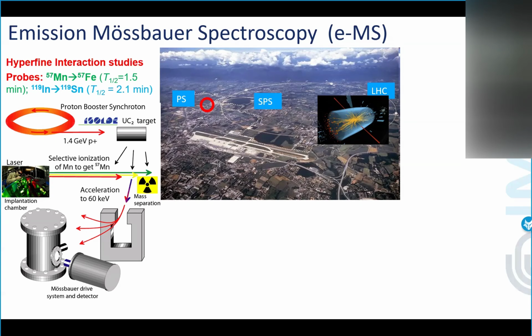So this can be used to induce nuclear fission in targets. In our case, we used uranium carbide targets, and plenty of species of atoms come out following the nuclear fission, and then following a very precise and accurate laser ionization, you can produce a highly pure beam of manganese-57, highly pure meaning 99.9 and something percent, and this can be directed to your implantation chamber, to your sample, which is usually 1 by 1 centimeter typically, and it decays to the Mössbauer level of iron. So from manganese-57, it transforms to iron-57, and this makes your sample the source, okay?